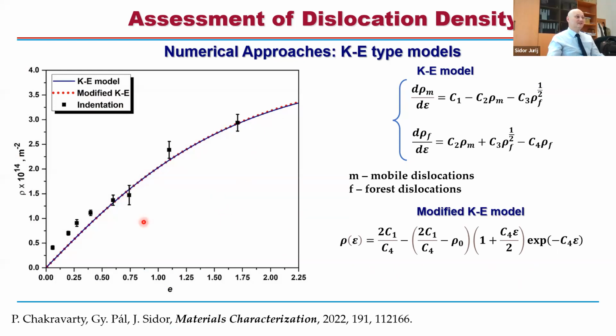Right, so here are the results of the modeling. So the K-E model and the modified K-E model are basically the same. And for our experimental points, which were measured by hardness measurements, we observed, I would say, a really very good correlation between the model and the experimentally observed data. We published this result recently. You can see them in Materials Characterization. So in fact, you can predict the evolution of dislocations by having information about the amount of strain which tends to develop during the rolling.